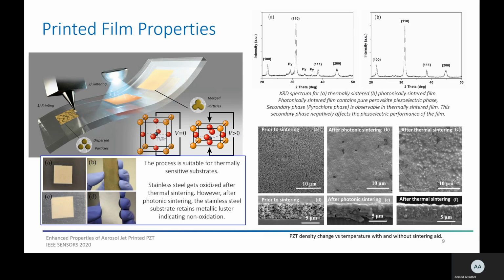Scanning electron microscopy images of the PZT films, top side and cross section, were captured as a qualitative measure. Prior to sintering, the particles were uniformly distributed in the film, as you see on the left-hand side. After photonic sintering, they are more fused together, with a better and smoother result compared to the thermal sintering. There are a few cracks that can be improved in the future by adding nanoparticles with sol-gel PZT or adding crack-bridging additives such as platinum. The XRD plots indicate the pyrochlore phases, with the left-hand side for the thermal sintering and the right-hand side for the photonic sintering.